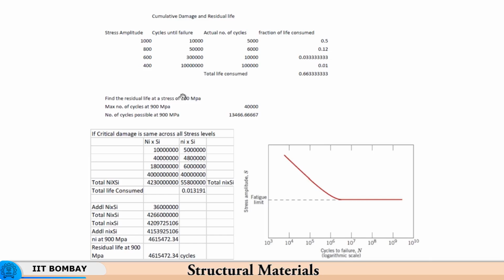Now, I want to find out what is the residual life, how long will the product last if I am going to load the material at 900 MPa. I do not know how much life it is going to have. Now, if I have tested, if I know that at 900 MPa a fresh workpiece will last for 40,000 cycles. Now, this workpiece has gone through use for a significant number of cycles. So, naturally I cannot assume that to be new and say that okay, it will last for 40,000 cycles at 900 MPa. So, now I have to find out how many cycles would be possible at 900 MPa.